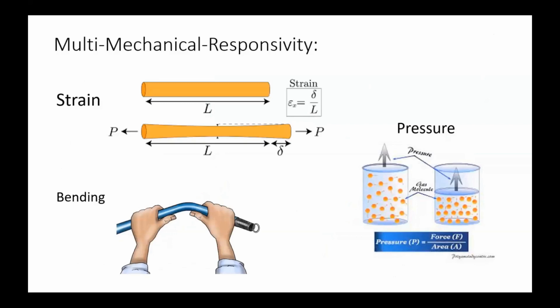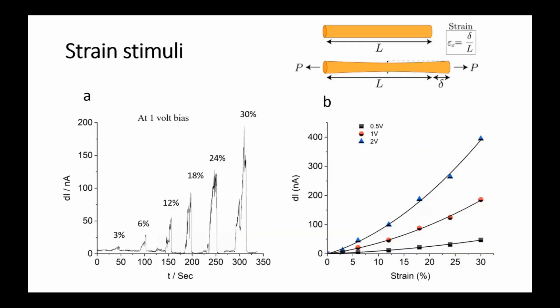Another stimulus in the same latex, in the same blend of material: we can even sense multi-mechanical responses like strain, bending, and pressure. As you see here, we take the film and strain it by 3, 6, 12, 18, 24, and 30%. I mean percent is the delta divided by L0, which is the length of the original film. We can see the response, and we can modulate this response and sensitivity by applying a different voltage.